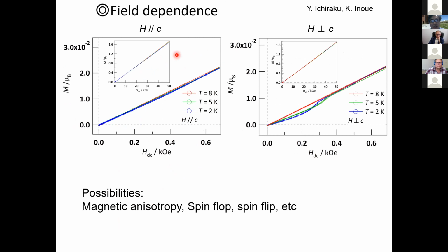And let's measure in more detail. This is the field dependence of magnetization at a very low field. This is parallel to C. This is the magnetic field applied parallel to the helical axis. This is perpendicular to the helical axis. As you can see, below TN, which is 8 Kelvin, you can find some anomalies in the magnetization curve. There is some possibility of magnetic anisotropy, or spin flop or spin flip or something.